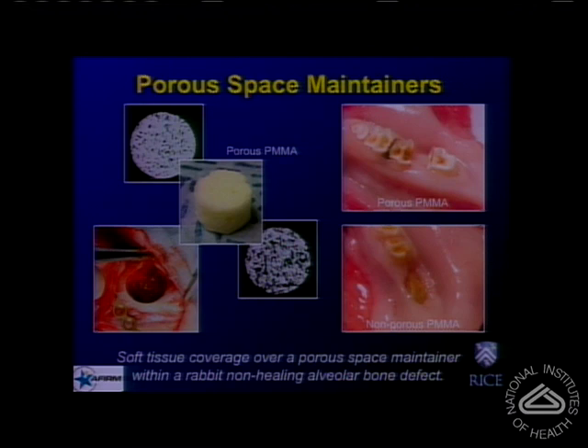There is a 2 to 3 millimeter notch in the superior border of the defect that allows communication between the mandibular region and the oral cavity. And we use porous materials to fill this region. We investigated the effect of the porosity on the healing of the soft tissue, the oral mucosa.